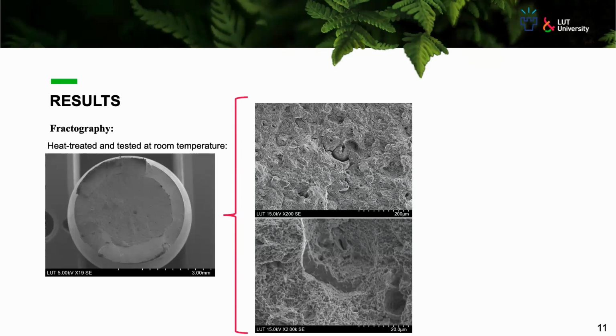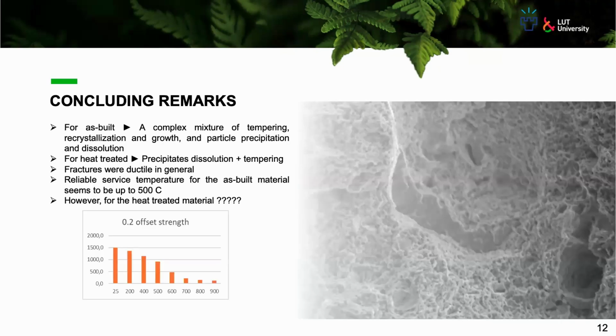The presence of some intergranular microcracks was also apparent. And on the micrometer scale, we also detected some brittle cleavage failures. However, their presence was not so apparent as to cause a brittle fracture in the specimen. And this is ongoing research, so this was the most difficult part for me to make a concluding remark.